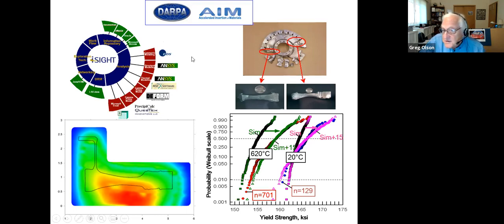And first, it was then used to couple to heat transfer simulations and predict the spatial distribution of microstructure and strength in a turbine disc. Which was then applied to the process optimization in a subscale disk whose performance was validated by overspin burst testing. And then we went on to the most challenging problem, which is